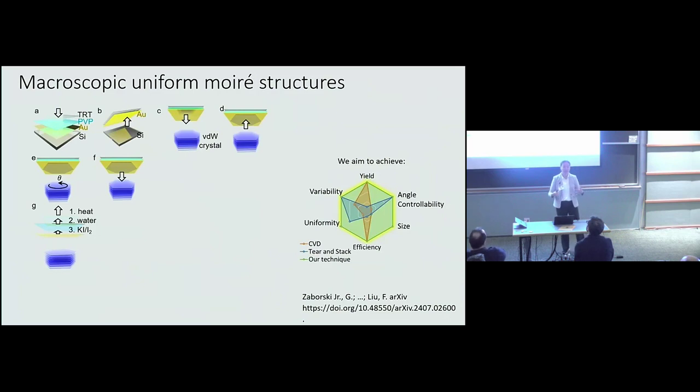So I would expect that to be the cleanest surface you could achieve for any of these monolayer surfaces. So we just take advantage of that super clean interface of the pristine bulk crystal, and we twist it at a small angle and just put it back. With this, we can create a twisted van der Waals interface at the top layer of a bulk crystal, and that would be the cleanest twisted interface we can ever achieve.